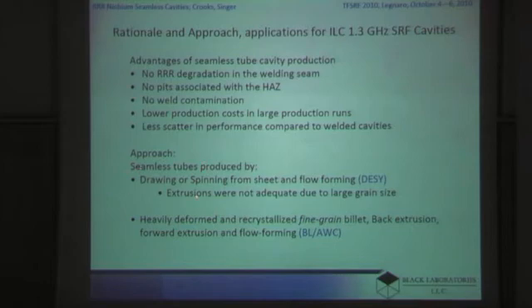In the work at DESY, after trying a variety of spinning and drawing methods, they chose a method of producing tubes from sheet by spinning or deep drawing, and used those after flow forming to provide the tube for hydroforming. Their work with extrusions were not adequate due to large grain size. The difficulty with using tube that's produced by the deep drawing method, for instance, is that the total length of the tube is limited by the width of the sheet. There's only a certain length of material you can produce in a rolling mill, and tubes of great length with uniform microstructures haven't been produced.